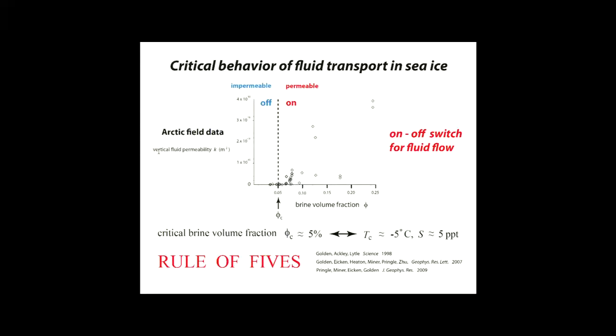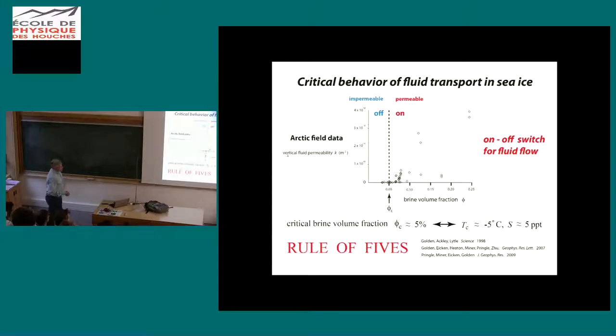Now, certainly one of the most exciting things that I've discovered in my career has been effectively what I would call the on-off switch for fluid flow in sea ice. Roughly speaking, for brine volume fractions below about 5%, the sea ice is effectively impermeable. And then for brine volume fractions above 5%, it's permeable, and increasingly so for increasing temperature or brine volume fraction.